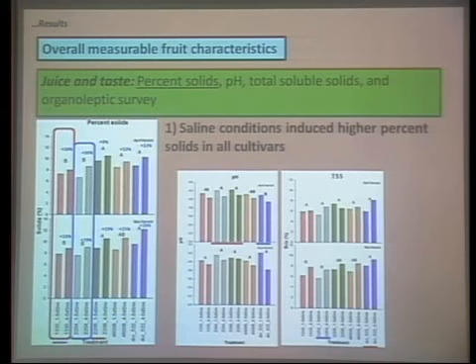In the pH and the TSS, we didn't see any effect, not in the interaction, not in the salinity effect, and not in the cultivar effect, neither for the April harvest on the TSS, nor for the main harvest on the pH. But we put the results here so you can see that the values averaged 4.2 for the pH and 6 for the TSS.